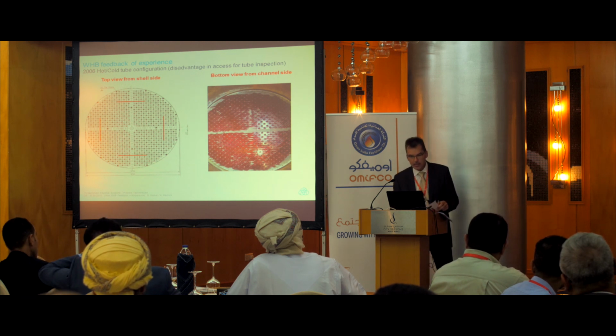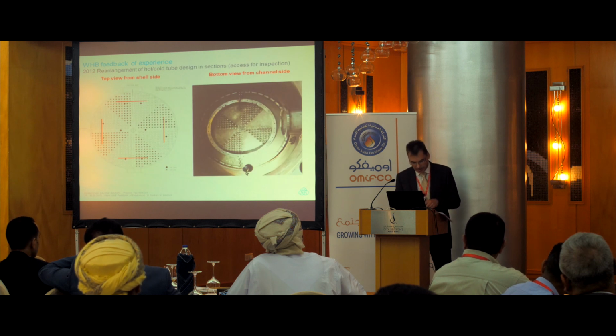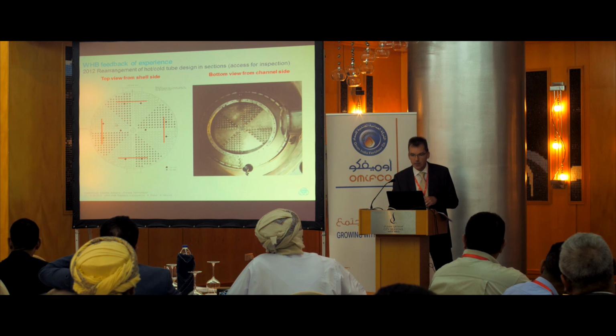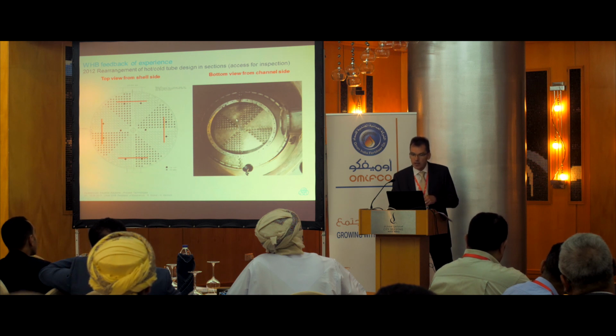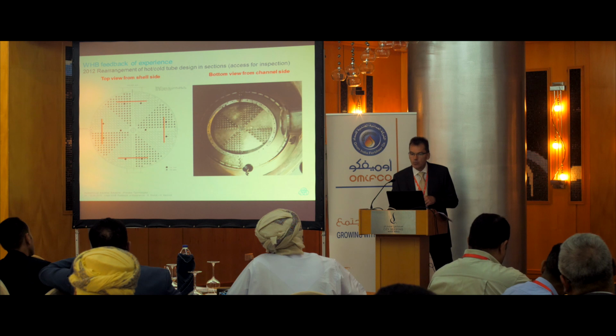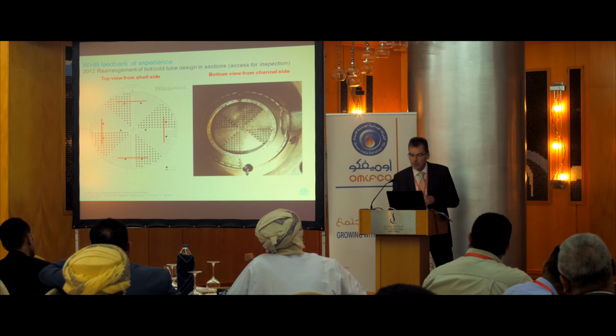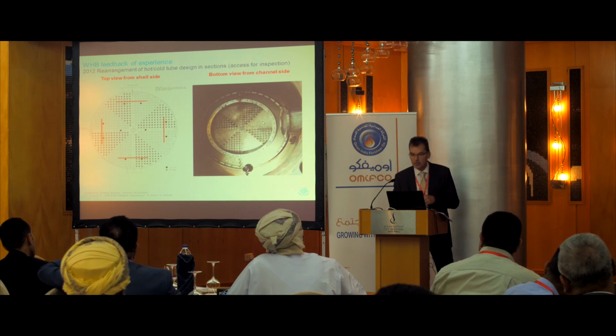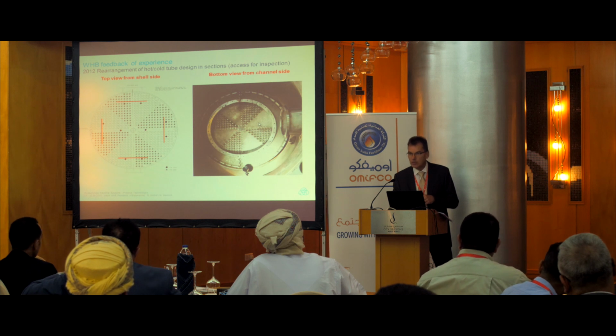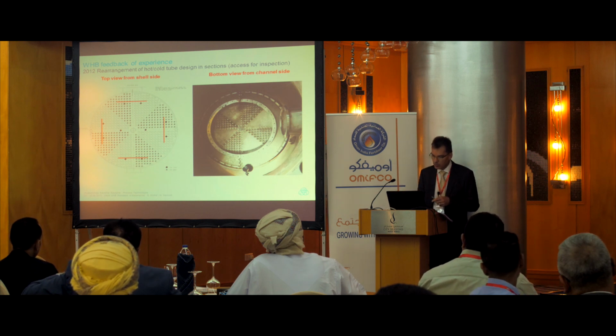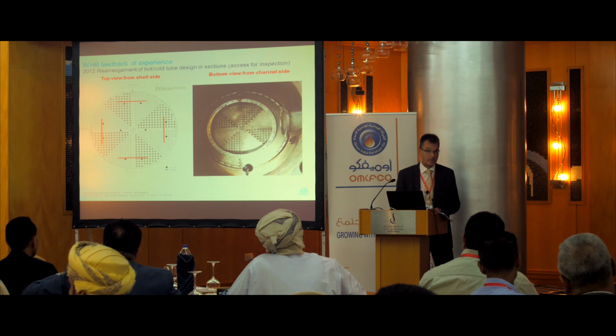Therefore, we changed slightly the design and said the tube configuration was basically kept the same. Look at the left side, but we invented here some covers on the false tube sheet. Underneath the covers are the ending of the hot-cold side, and we can remove these covers during inspection, and we can see the hot parts, which you see here clearly, and when you remove this cover, you can see also the cold parts, and you can identify then easier where is the leaking tube. Even during the hydro test, you see where is coming water out. Of course, we don't want to have leaks there, by the way.